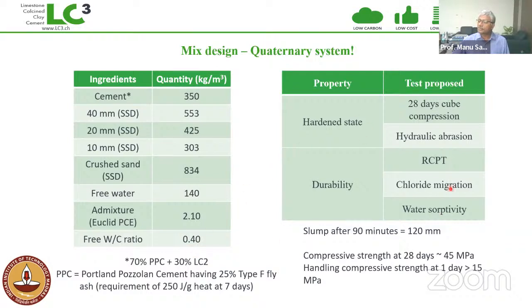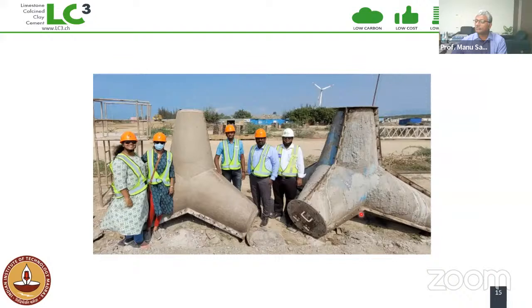And with this, of course, we are monitoring various different qualities of the concrete with time. The compressive strength at 28 days that we obtained was about 45 megapascals, much more than their requirement of 37 megapascals. And even at one day, sufficient compressive strength of 15 megapascals was available, because that is required to remove the molds and then handle or lift the tetrapods and bring them to the stacking yard. And this is the team with my students and the people from L&T who are there to execute this project. L&T is really interested in taking this forward. They are very excited about using LC3, especially in these kinds of applications.